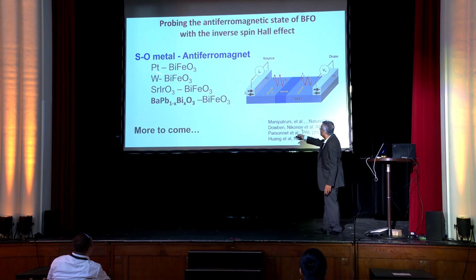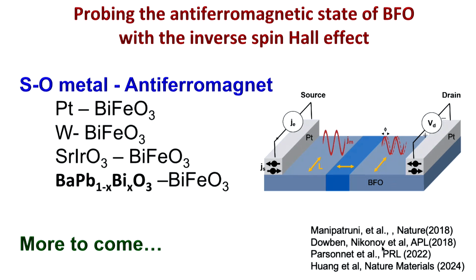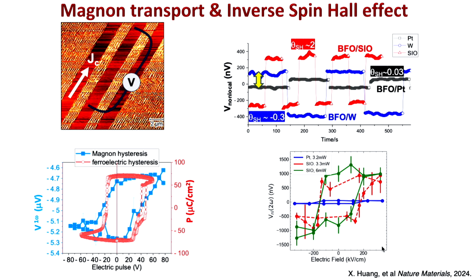So I want to show you a piece of data where we have a spin orbit metal, not platinum or tungsten, which is the metal that everybody has been looking at, but these are correlated metals. These are metals like strontium iridate or barium lead bismuth oxide. Strontium iridate behaves very much like a topological insulator. So we've been doing spin Hall and spin Seebeck measurements. And this is the essential data.